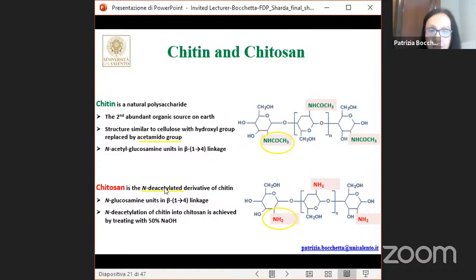As you can see here, chitosan has polar functional groups in the structure, specifically hydroxyl, here, primary amine, and ether groups, that facilitate the chemical modification of chitosan. Also, chitosan chains are bonded through intra- and intermolecular hydrogen bonding, responsible for the good film-forming properties.